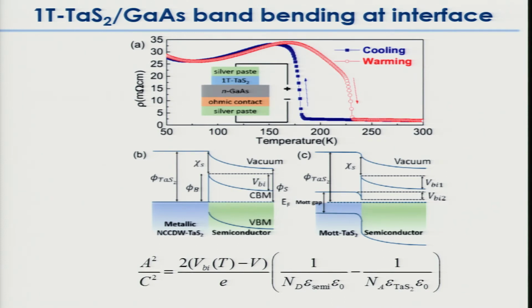But we now have two contributions. And it turns out that ND, the density of donors, this term is a lot smaller than this term, so we're essentially dominated by it. The band bending here is a lot smaller than the band bending in the semiconductor. So we now are going to look at this structure.